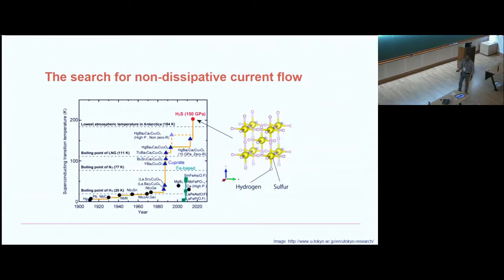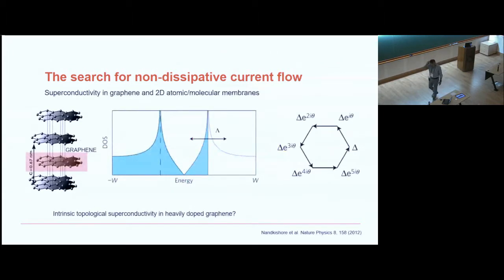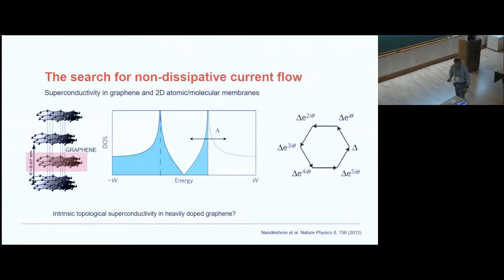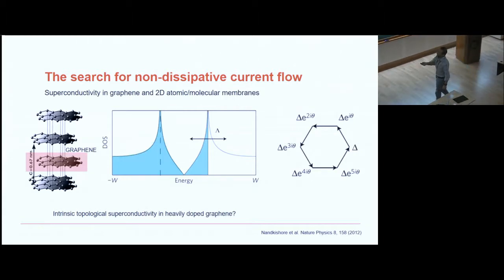However, in the early 2000s, we started looking at graphene. And as far as superconductivity is concerned, they started coming with very interesting new kinds of dissipationless flow. For example, in the case of graphene, you have a possibility of doping it to 10% or 12% of electrons, and then it's theoretically predicted that you will be able to get new kinds of superconductivity, like a topological superconductivity, where the order parameter winds around in a d plus id kind of symmetry. Okay, I'm not going to talk about these at all, but these are experimental systems that we are strongly working with and trying to dope sufficiently heavily so that we can achieve these new phases of matter.